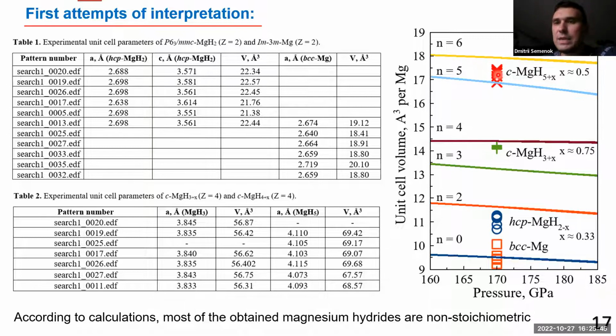And it means that all of those obtained magnesium hydrides are non-stoichiometric compounds. We always need to add some additional hydrogen to explain why the experimental volume is higher than theoretically predicted. For magnesium H5, it's about 0.5. An additional half of a hydrogen atom should be added. For magnesium H3, it's actually much bigger. It's much closer to magnesium H4, according to theory.